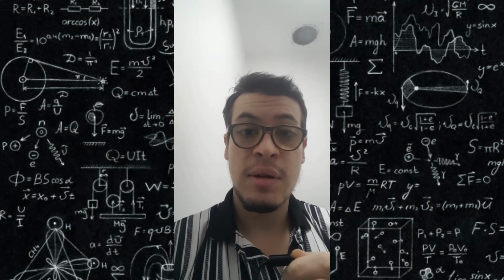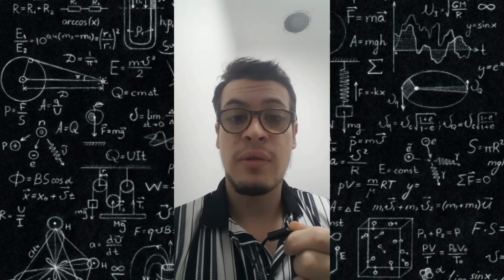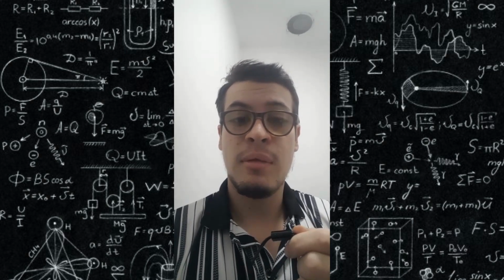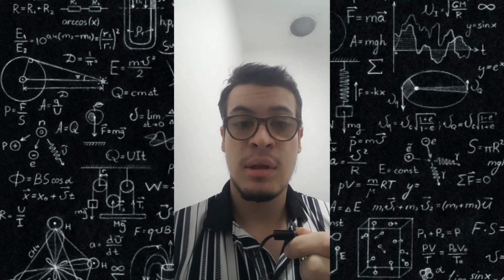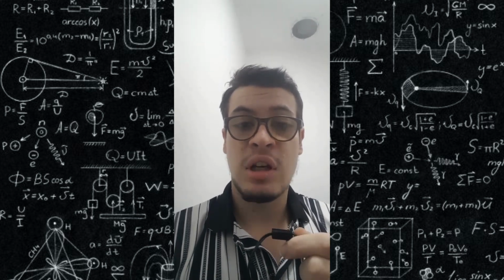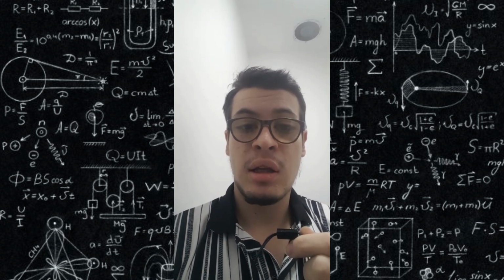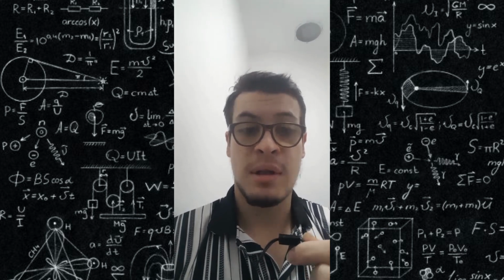Results: the artificial cracks with different values of length, width, and depth, with rectangular and triangular shapes, were formed using an electrical discharge machine at the center of the specimen. The authors of this work focused on the surface cracks, and the distribution of the magnetic field on a crack is similar to the shape of the crack. That is, the sectional views of the magnetic field are similar to the rectangular or triangular shapes.